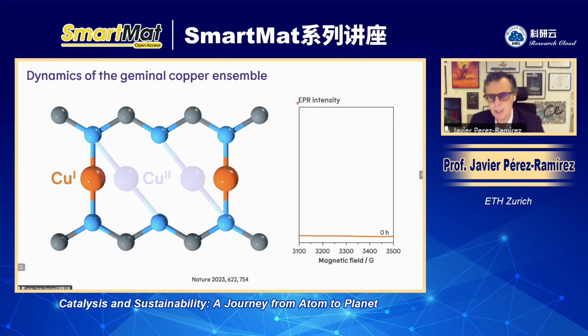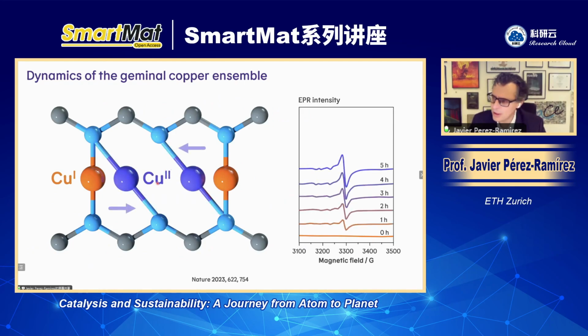And this is operando electron paramagnetic resonance spectra upon a cross-coupling reaction. At time 0, before the reaction had started, we have the ground state of the copper atoms. And these copper atoms are actually copper 1 atoms. Copper 1 is silent in EPR, and that's why we don't get any signal. Now you put the reactants that you want to couple.